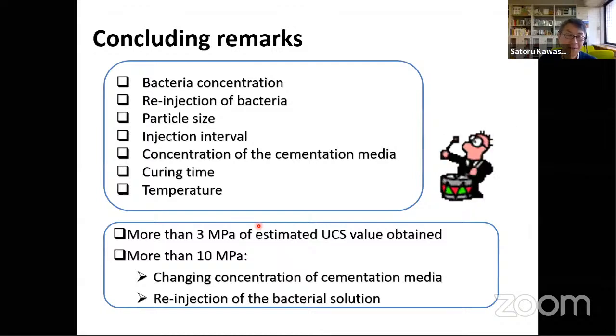So shall we conclude today's presentation? We focused mainly on bacterium concentration, injected or re-injected bacteria, particle size, injection interval, concentration of the cementation media, curing time and temperature. Some of the content we skipped due to time limitation, but we discussed it in our laboratory. Up to now, we obtained more than 3 megapascal estimated UCS, and more than 10 megapascal, changing the concentration of the cementation media. And when re-injecting bacteria solution, we could obtain higher strength samples in UCS.